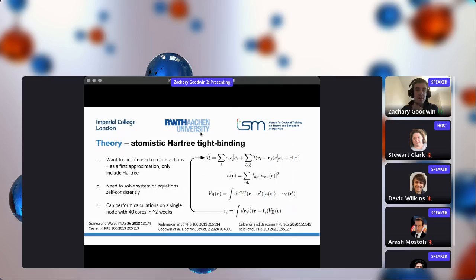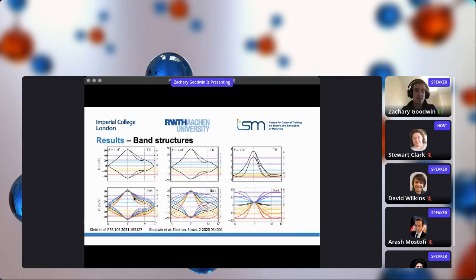So we did this by developing an atomistic Hartree tight binding theory. What we do is we start off with our non-interacting Hamiltonian, and we construct the electron density of this system, which we can then use to construct the Hartree potential that the electrons feel. And that can then be included as an on-site energy in our Hamiltonian. Essentially we need to self-consistently solve this system of equations, which is fairly expensive to do with Hamiltonians that are the size of 12,000 by 12,000. But to put it in comparison with ab initio methods, I can do this self-consistent calculation on a single node with about 40 cores in about 2 weeks. So that's substantially cheaper than using a DFT code.